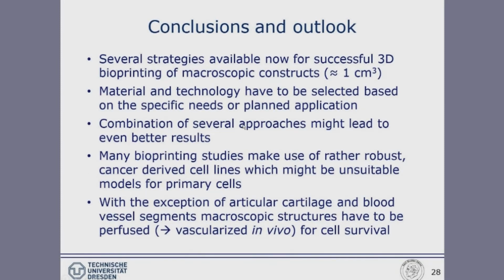Maybe combinations of several of the approaches I have demonstrated might lead to even better results, and I have demonstrated a couple of them. For example, the combination of external stabilization, think about the calcium phosphate bone cement, and the already internally stabilized, rather stiff bioink. The blend of alginate and methylcellulose needs maybe two especially interesting properties.